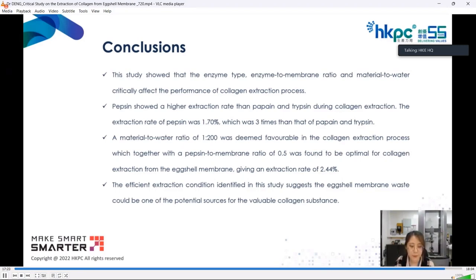This parameter was found to be optimal for collagen extraction from the eggshell membrane, giving an extraction rate of 2.44%. The efficient extraction condition identified in this study suggests the eggshell membrane waste could be one of the potential sources to obtain the collagen.